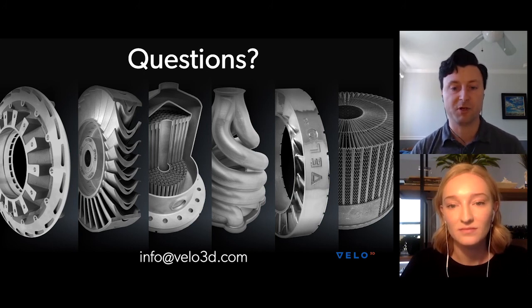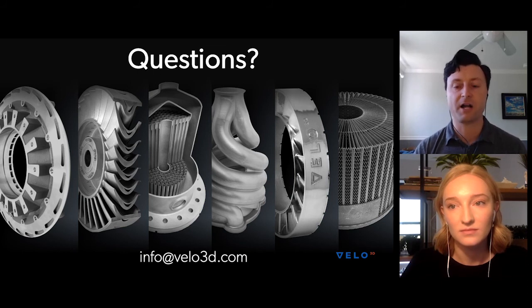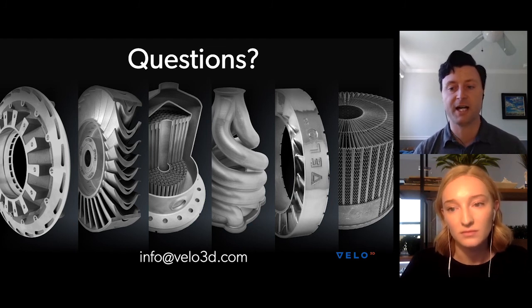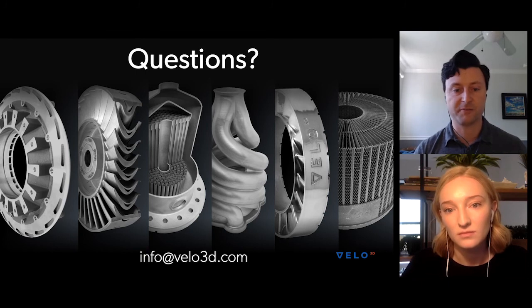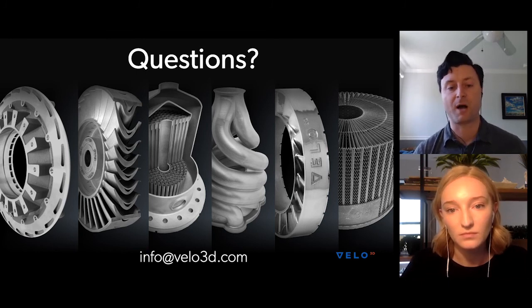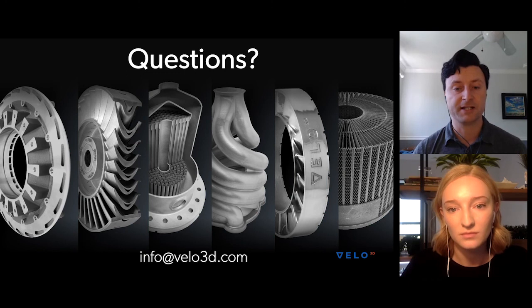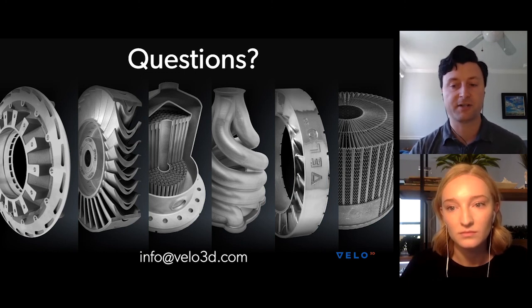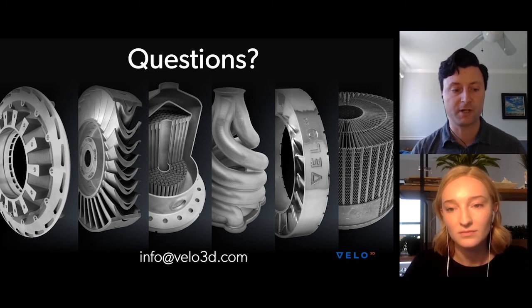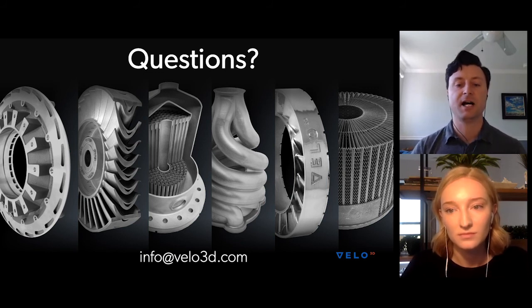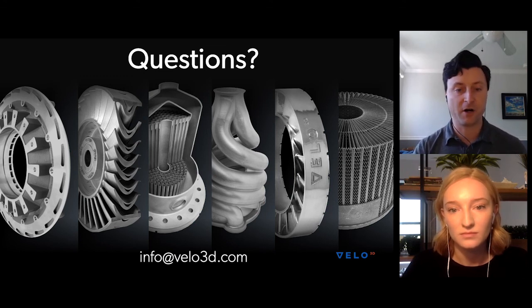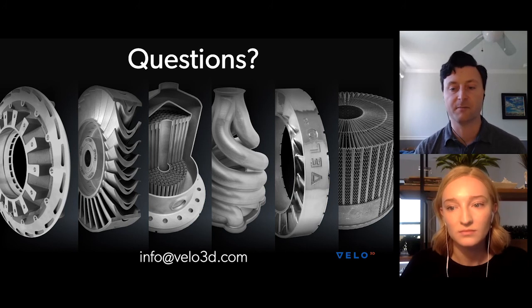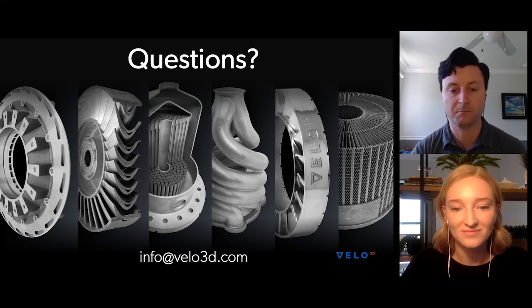Regarding melt pool monitoring, we absolutely have melt pool monitoring, and I think the more important thing than just the monitoring is that our Assure quality assurance software is actually interpreting that data and giving the user actionable feedback around defect detection, both in terms of the porosity of the part, so the probability of pores being formed in the core material, and then also from surface roughness. And so like in a manifold, when you have internal diameters that are very hard to kind of scope or CT, depending on the material, our system actually can show if there are surface defects that are caused by, as an example, like a melt pool instability. So those are two very powerful metrologies that come with the Sapphire system.